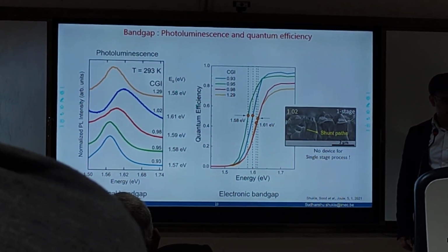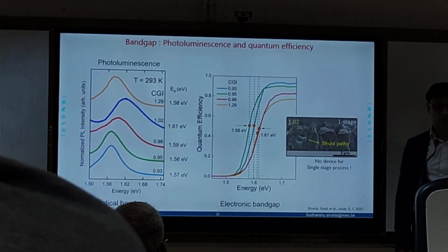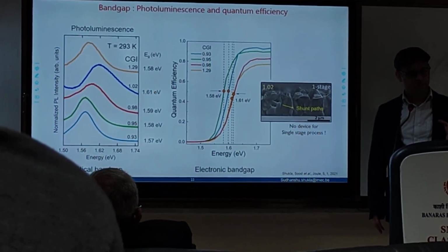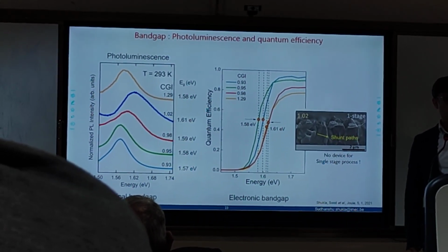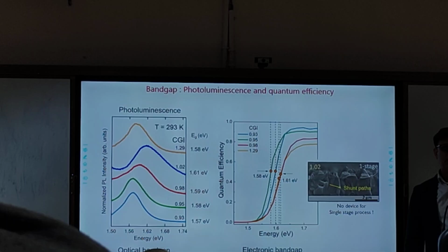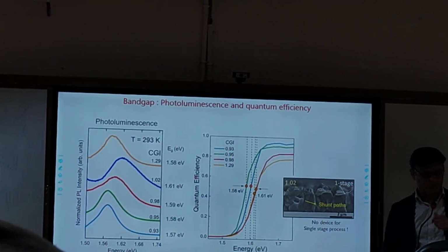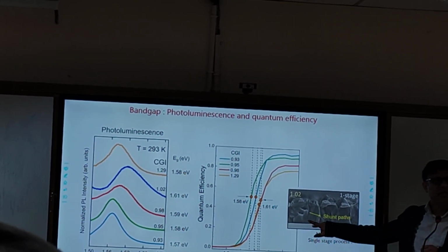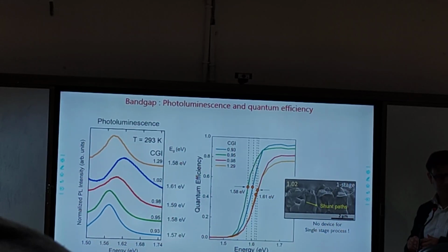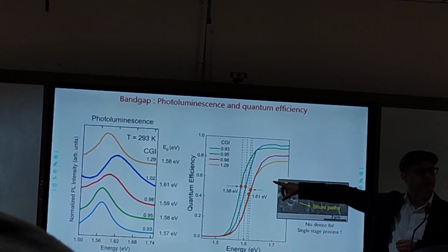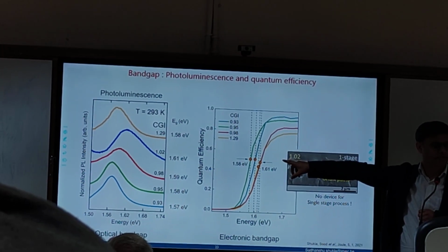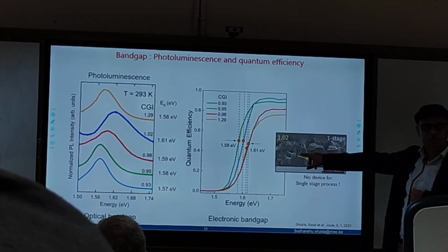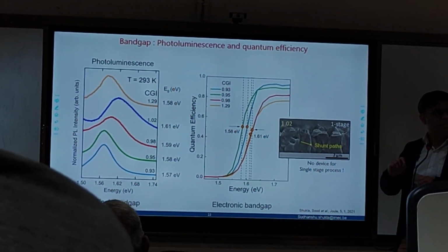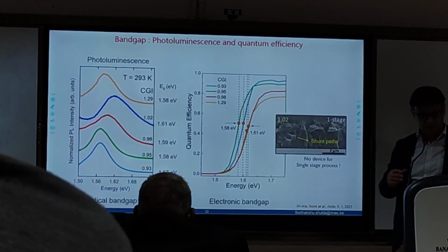Then, with these good old measurements of photoluminescence and quantum efficiency of our solar cells, we find out the band gap. PL is something you are very familiar with, so I'm not going into the detail, but there are two things I want to highlight here. Why I did two measurements, not just one. This is more of an optical band gap, what you get from photoluminescence. What you get from quantum efficiency, an electronic measurement, is more of an electronic band gap. They can be different, okay?